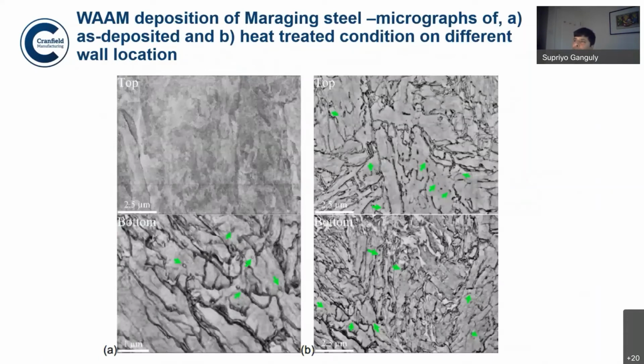Now I'm showing on the left hand side the two micrographs. The top one is taken from the top of the deposit in as deposited condition, and the bottom one is from near the bottom of the deposit in as deposited condition. The right hand ones are the same after heat treatment, and they show some amount of precipitation after the heat treatment, and that's why the hardness has jumped up.